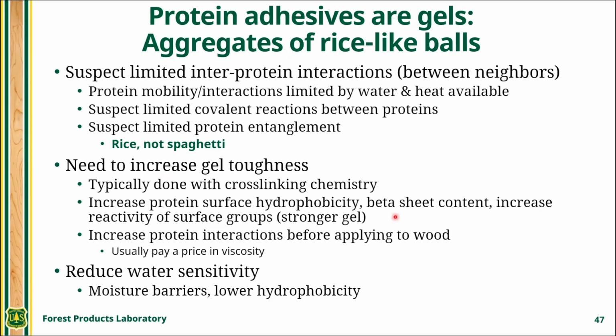Here's some other ways that maybe the gel strength can be increased. Surface hydrophobicity, beta sheets, surface reactive groups. And you can increase protein interactions with their neighbor in some processing step before applying it to the wood, such as jet cooking. However, I have always seen, and it makes logical sense to me, that if you build structure and you build these larger protein complexes before you apply them to the wood, you pay the price in viscosity. So the more hydrophobic surfaces and the bigger the particles, the higher the viscosity. And that's a challenge, to be sure.